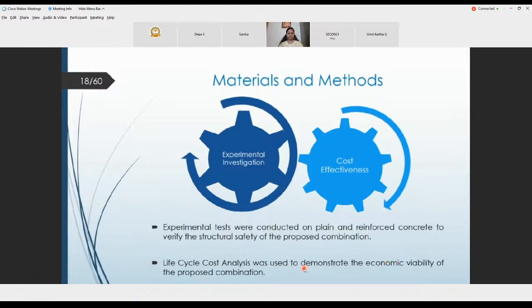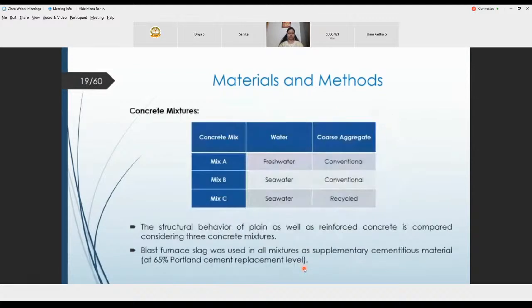The combination we're talking about, again, is Seawater, RCA, and FRP. For doing this, we created 3 mixes: Mix A, B, and C. We'll be using these throughout the presentation. Mix A uses fresh water, and the type of coarse aggregate is conventional. Mix B uses seawater, also coarse aggregate conventional. And mix C uses seawater, and the type of coarse aggregate is the recycled coarse aggregate.